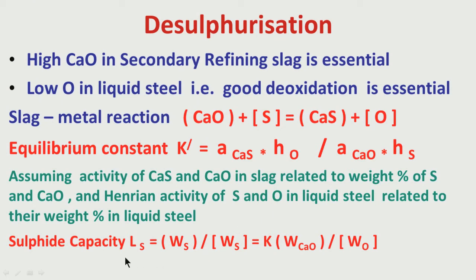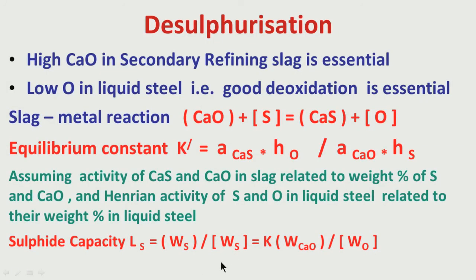So, what is the sulfide capacity? It is a new term. Sulfide capacity is the wt fraction of sulfur in slag, first bracket, divided by the wt fraction of sulfur in liquid steel, third bracket. So, what is happening? The sulfur from liquid steel is going to sulfur in slag as calcium sulfide. That means the wt fraction of sulfur in slag divided by the wt fraction of sulfur in liquid steel. So, the more this ratio, the more is the desulfurization. Is it clear?